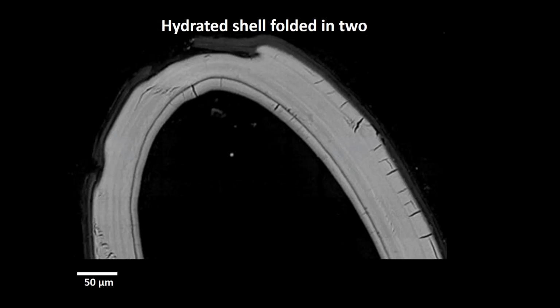I mean, they're very thin, so you can break them quite easily. But for the material, they're a hard material. But if you soak them in water for long enough, and by long I mean about an hour should do it, they become very flexible to the point that you can fold the shell in half and it doesn't break.